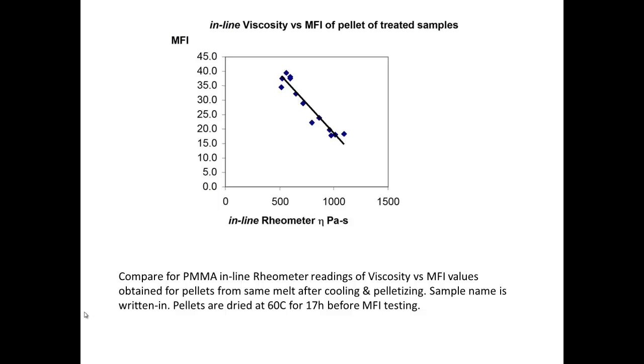So I have succeeded in obtaining, in pellets, a sustained orientation, which is a melt which is no longer, if you want, a stable melt, or at least it's stable long enough that I can measure the differences. But this melt, as we will see, loses little by little its stability, and tries to return to the initial value of entanglement that it had in the virgin, untreated sample, and it takes a very long time. So the understanding of what we are describing from the established theory is non-existent.